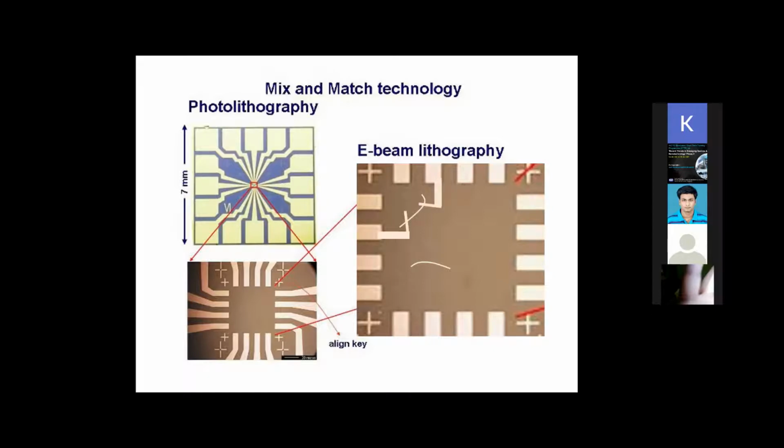So we do this or achieve this with e-beam lithography. Actually, we first locate the nanowire using the secondary electron imaging system, then find out its position compared to the alignment marks like the cross. We calculate the distance of the nanowire from this marker, make such a program, and then we again do a e-beam writing. Now while e-beam writing, we keep in mind that initially from the pad we should progress a bit, and then in a second step of writing we will ultimately connect it.